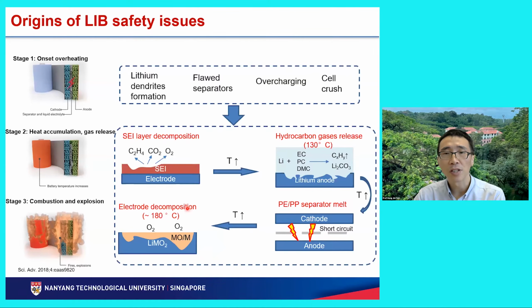Electrode decomposition is another cause: the cathode material itself may also be unstable. At high temperatures, if your cell goes to 180 degrees, then the electrode material is also unstable. They also release gases, and once they release gases, the whole thing will swell and generate a lot of heat in a short time.